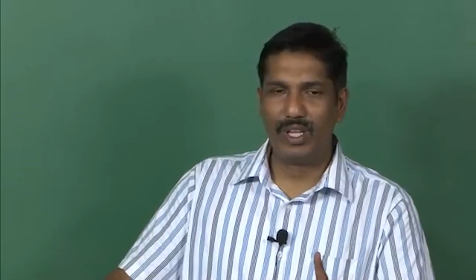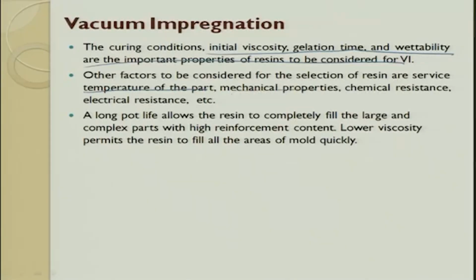The matrix distributes the load, the fiber takes the load. If the fiber has to take the load, the wettability has to be very good. Other factors to be considered for selection of resin are the service temperature of the part, mechanical properties, chemical resistance and electrical resistance. So, these are all for choosing a proper resin. We have seen enough of resin properties. So, you choose a proper resin to meet your application. The long pot life allows the resin to completely fill the large complex part. What do you mean by long pot life? The gelling time does not start, the resin does not cure, the resin is still nascent for a longer period of time such that it could completely wet the reinforcement, so you get the best out of it.